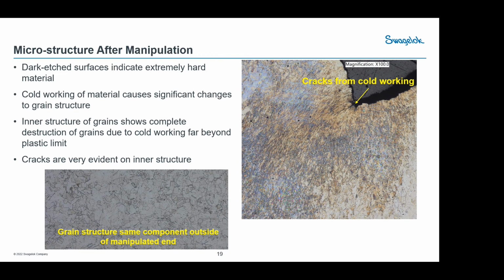The other thing is that this is the same piece of tube. So if you look in this center area here, it looks like pieces of paper laying on top of each other. That means that the grains that were nice and pretty in this bottom picture have been totally destroyed. They're crushed together, and that grain has changed the consistency of what this material is. And that can happen when you cold work materials. That means this may not actually be 316 anymore. There's probably a high possibility that there's martensitic phase been added to this, which in the world of hydrogen and embrittlement is in the category of bad. So not a good thing to be taking place, but that's not the biggest problem.